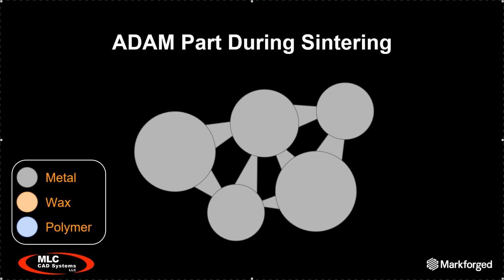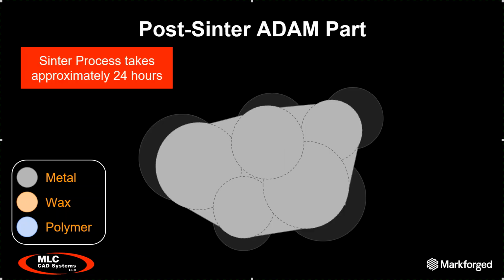And once you fire it up, the process will start to outgas and burn off the polymer, turn that into vapor, and it'll be vented. But the metal will start to melt. Now, this is the part that blew my mind, right? This is the part where I said, well, hold on a minute. You're melting it, and it doesn't just turn into a puddle. Sintering is just below the melting temperature. It allows the metal crystalline structure to merge with its neighbor and slowly grow the crystal boundaries, and they slowly start to merge together over time.